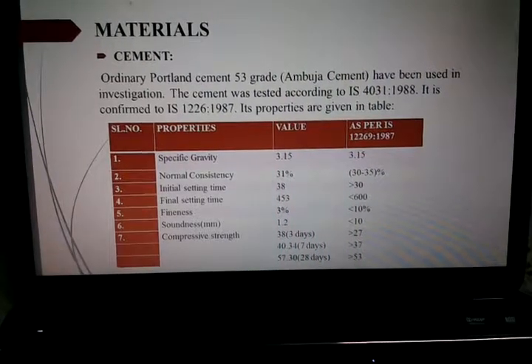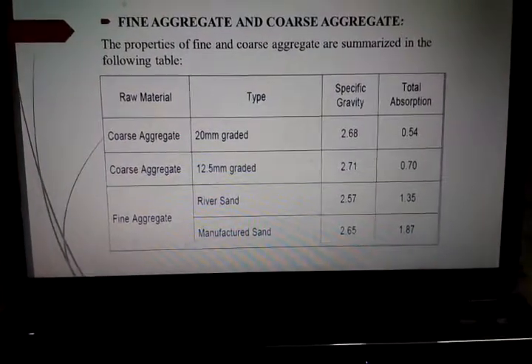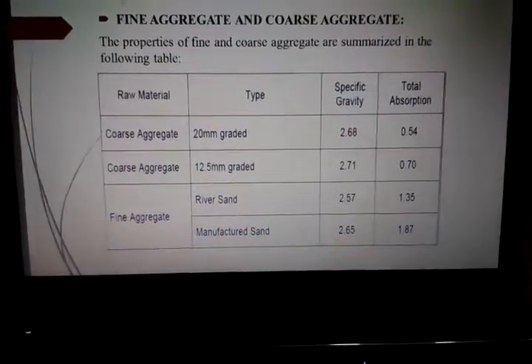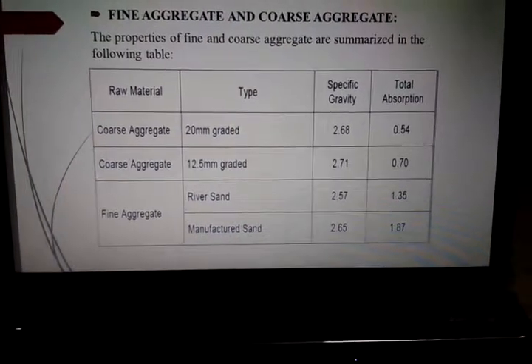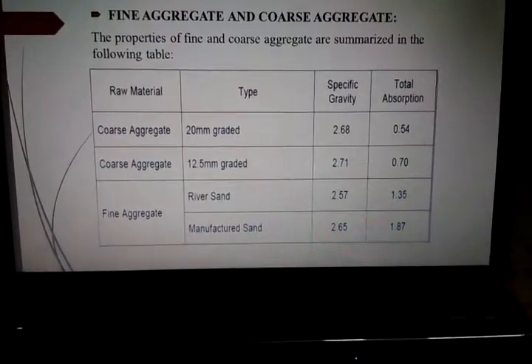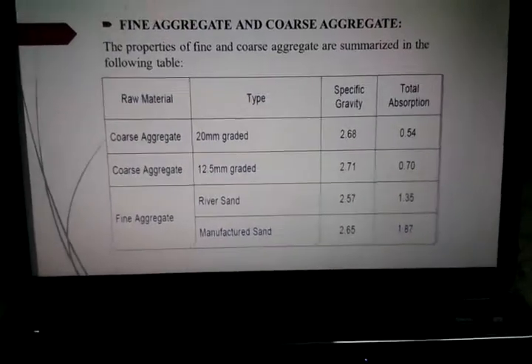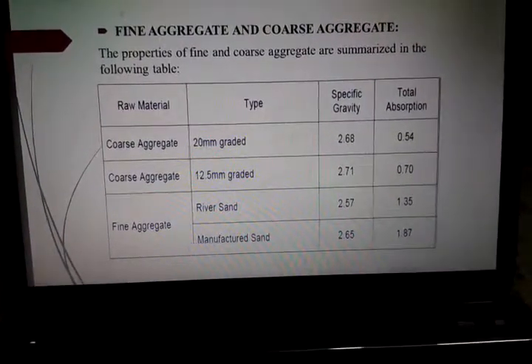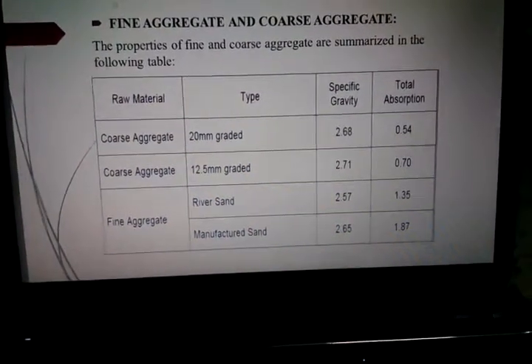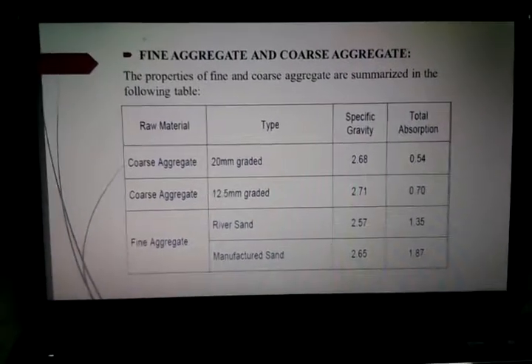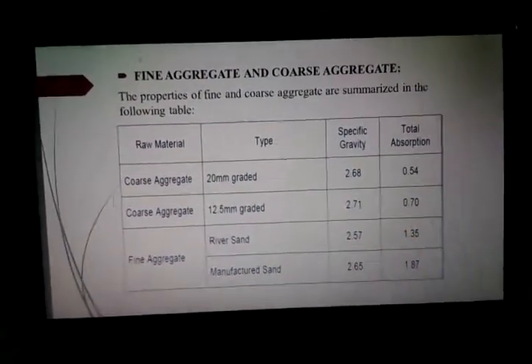12269 1987. Fine aggregate and coarse aggregate. The properties of fine aggregate and coarse aggregate are as summarized. Coarse aggregate of 20 mm grade and 12.5 mm grade are used. Specific gravity of the same is tabulated. The fine aggregate is generally manufactured sand, but we've also taken the specific gravity and total absorption of river sand.